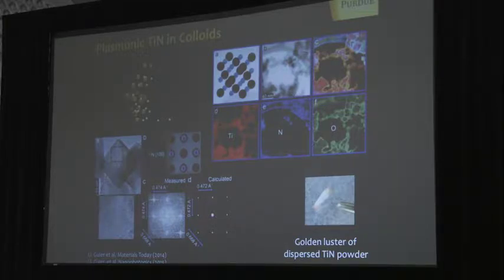And the important advantage you get in this case, as opposed to gold, which is polycrystal, is that these turn out to be single crystal colloidal particles. And since, of course, the lattice is cubic, the colloidal particles are cubic themselves, too. So it's single crystal colloidal particles, and that has been proven by using this diffractogram, and it's a very cheap way to make them. So that's yet another application, in this case of transition metal nitride, for photothermal therapy.